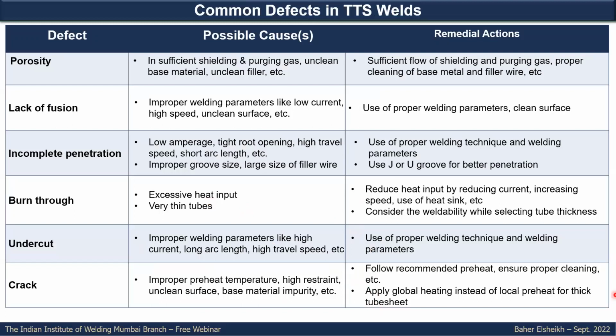Here is a summary of the most common weld issues we can see in the tube-to-tube sheet joint. Porosity might be caused by insufficient shielding or purging gas, or unclean base material or filler. You have to use a sufficient flow of shielding or purging gas and properly clean the weld area, the base metal, and the filler wire before welding. Lack of fusion can be caused by improper welding parameters, low current, or high speed. This is one of the famous issues in the tube-to-tube sheet joint, both lack of fusion and incomplete penetration.